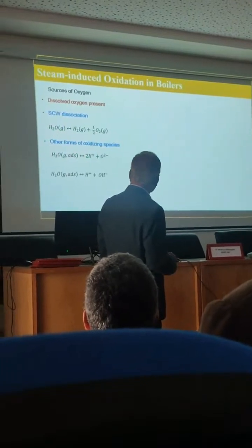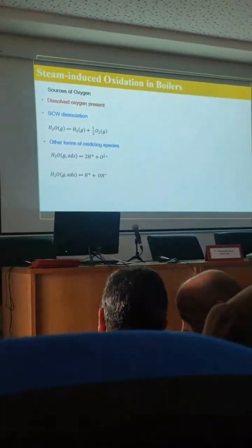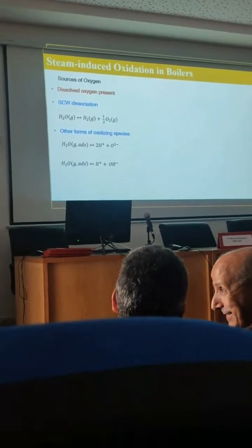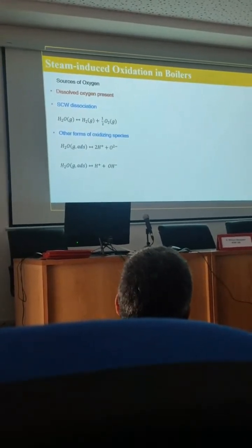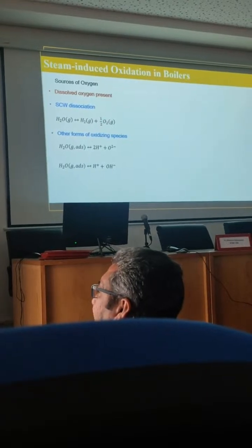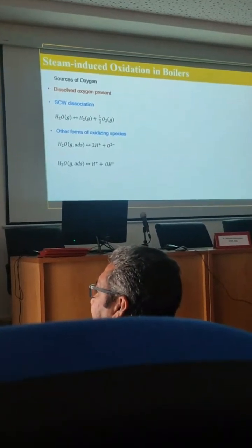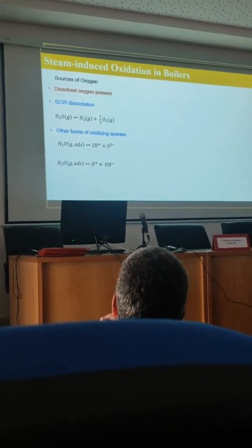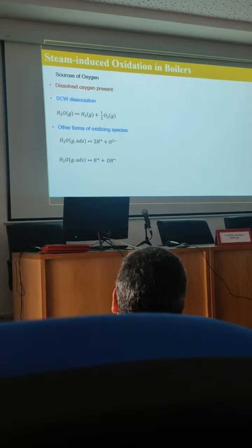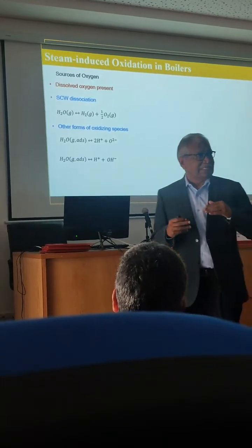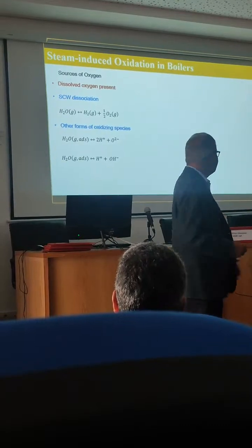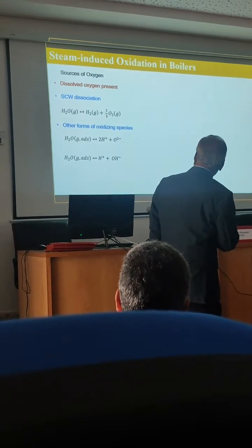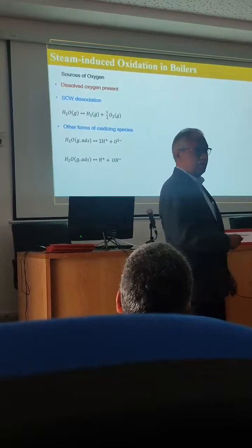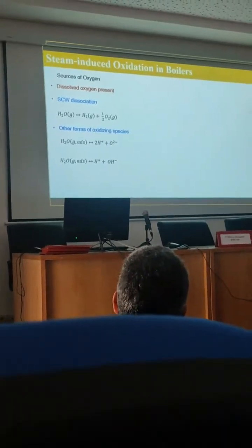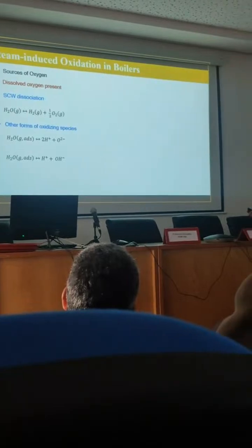So again, it's very interesting now. The water is not the same anymore. The temperature is so large that the water decomposes into hydrogen and oxygen. They dissociate into oxygen radicals, oxygen ions. So the water is not the same water. That means it is going to change its corrosion behavior because the water is decomposed into these species, and these species are promoting corrosion in the system now. So that's a real problem, right?